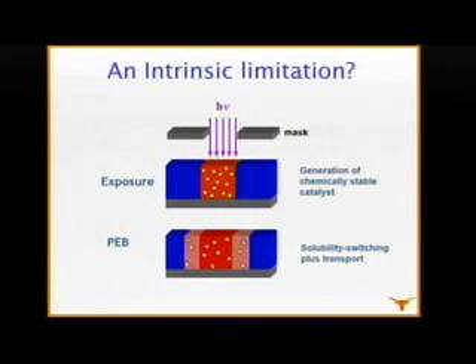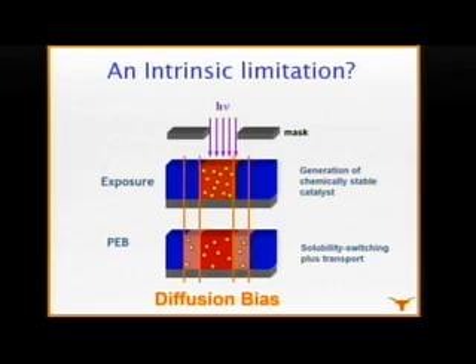So now, that's all a preamble to explaining to you what the problem is. What happens is you shine light and you make a latent image of acid in the film. The little dots are the acid, okay? And then you bake it and let the acid do its thing. And what happens is the acid doesn't understand that it's only supposed to stay in the area where the light struck the film. So classical mass transport doesn't occur, sort of non-classical mass transport occurs, and the acid diffuses sideways such that when you develop the film, the image that you produce is bigger than the image on the mask.